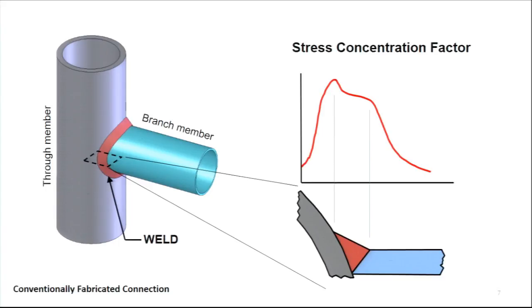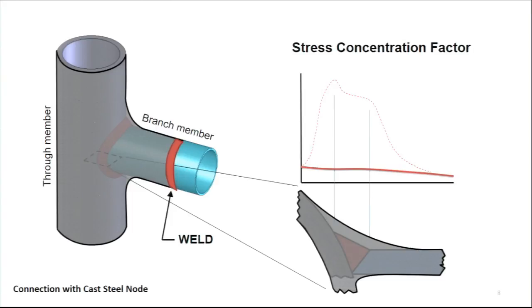Someone in the late 1970s, early 1980s, thought of using castings to address this issue in very complex structures. And the idea was if you replace that junction with a monolithic cast node, you can use the casting process to put the material where it ought to be for the flow of forces through that connection. So I could make that a very smooth and generous radius to reduce the stress concentrations through that geometry. And then I move the welded joint away and separate it from the geometric stress concentration. And so by doing so, we can significantly reduce the stresses in that welded joint and significantly improve the fatigue performance in that connection. And we can, as I said, improve the fatigue performance of those connections by an order of magnitude, a factor of 10, and that means that structure will last 10 times longer.